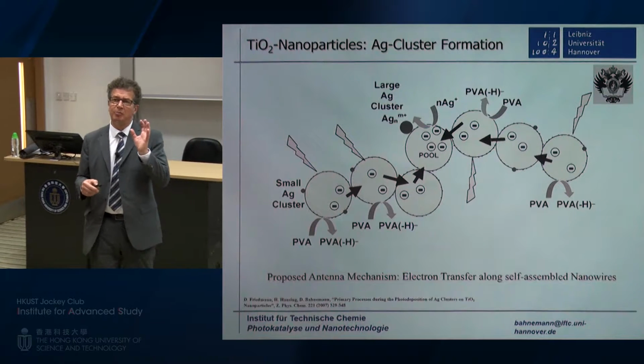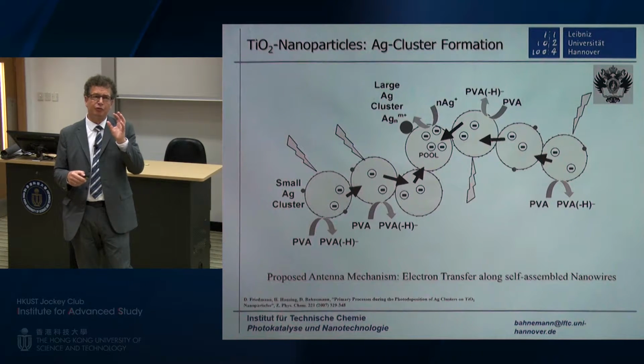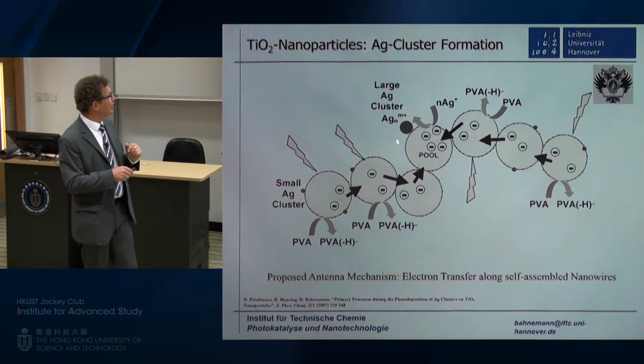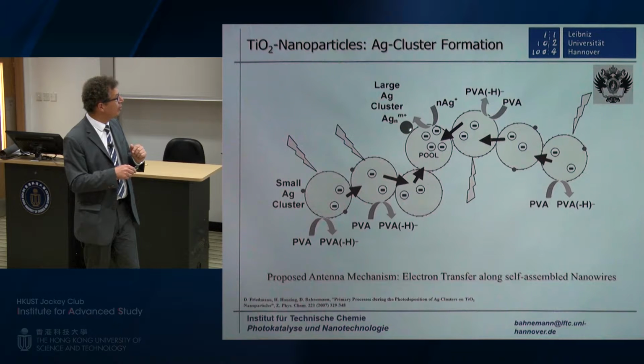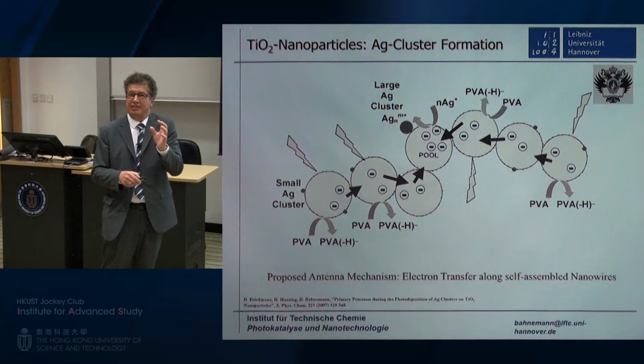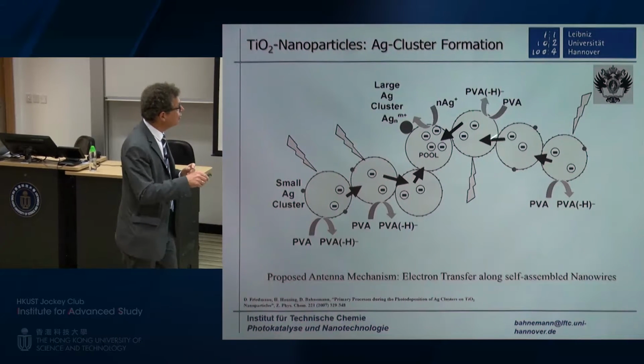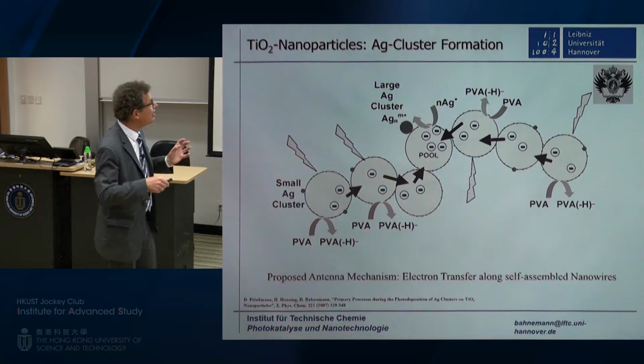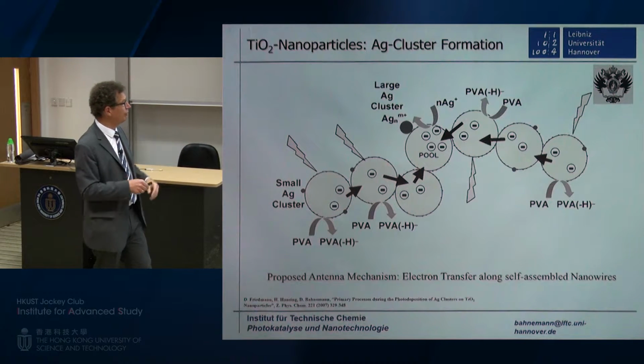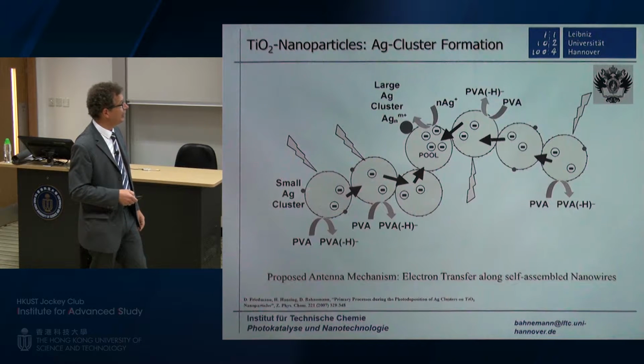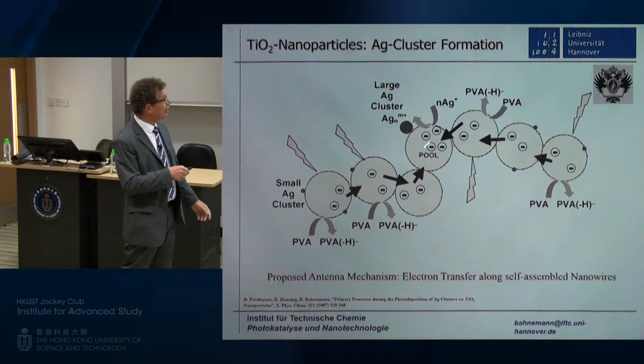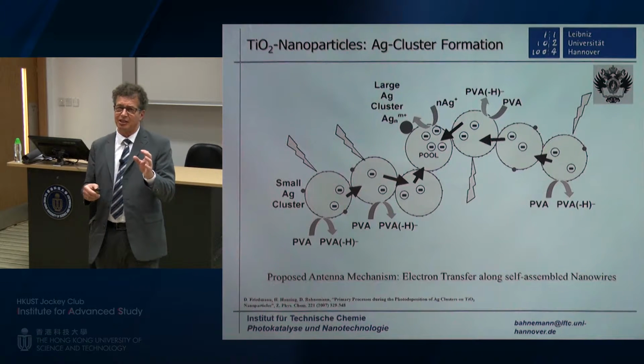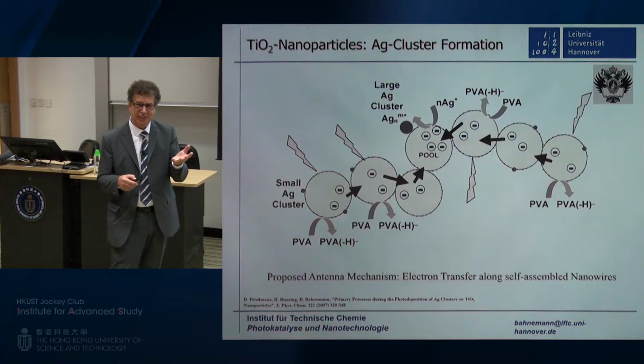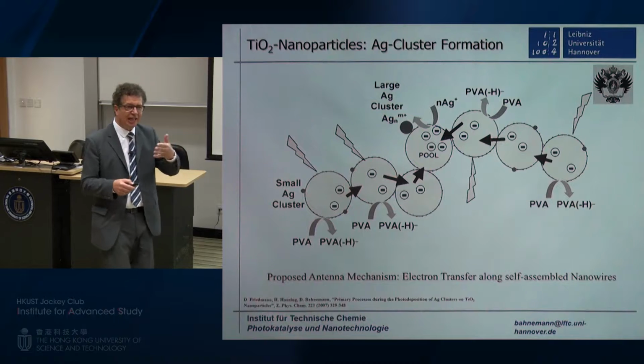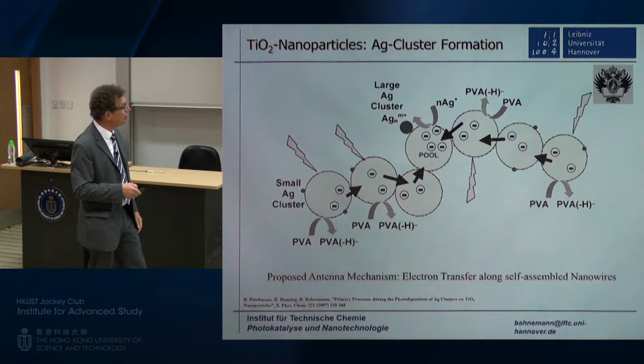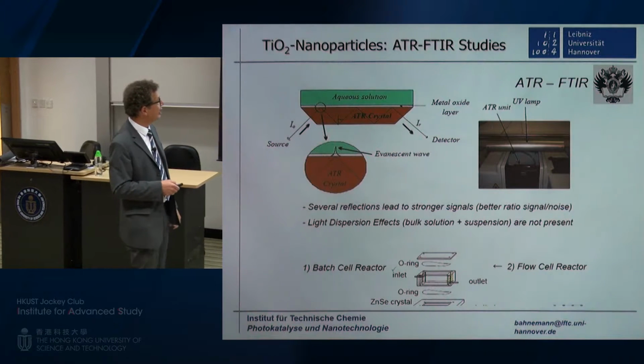And this seems to be a general mechanism of formation, because whenever we form as a photodeposition process these noble metal contacts, they are big. We don't form such a contact on each particle, but we form them on some particles exclusively, and the rest of the particles don't show these complexes. And actually, by the way, this electron transfer along these chains of nanoparticles is used, for example, in the dye-sensitized solar cells, also called Grätzel cells, where actually these charges are transported along titanium dioxide arrays.